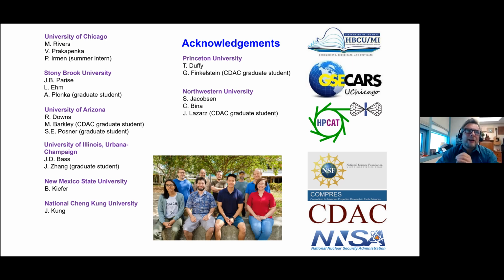Thank you. We also tried to use this concept of double stage compression. A lot of experiments, including diamond anvil cells and large volume presses, managed to achieve higher pressures by putting an anvil arrangement inside the high pressure device. So we thought that mixing our sample with something like diamond powder might serve a similar purpose. You would have these very hard, small crystals of diamonds present during collision and pushing even harder on the grains. But it's still underway.